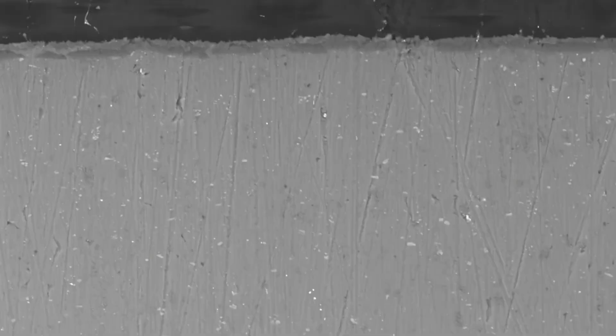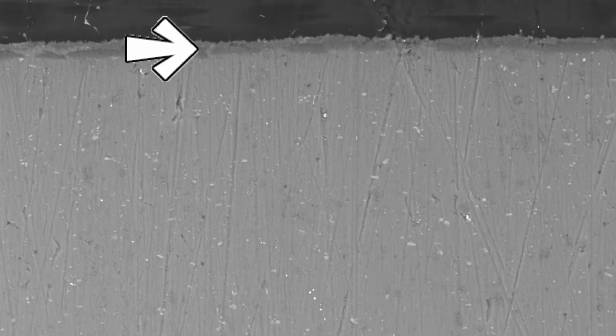Well, I know that everyone's probably interested in the gold stuff first, so let's start with the ring. We're going to use the backscatter detector, which will give us atomic number contrast, which means that heavy elements will appear bright and lighter elements will appear dark. So looking at it cut in half and polished, we can see the main body of the ring is this lighter color, while we can see this darker colored layer about 5 micrometers thick on the surface.